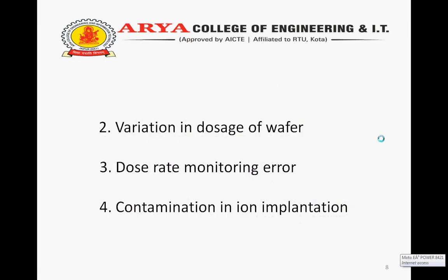Second is variation in the dosage of the wafer. Another problem with the tilt angle in a statically scanned implant system is that the dosage of the wafer will vary from one side to the other. This problem becomes more pronounced with a larger wafer where the electrostatic angle can be 2 degrees or more. High current implanters in which the wafers are mechanically scanned in both directions do not suffer from this problem.